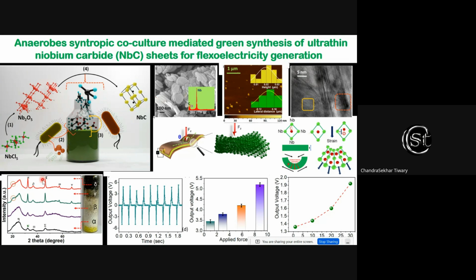Now the X-ray, and this is the reactor, it can clearly show this was the niobium chloride salt which we started with. It converts into oxide, and then slowly, because of the presence of microbes, it starts becoming black color niobium carbide, which can be utilized for energy harvesting, as a coating, and so on. And all of this material, the size, thickness, and dimensions are almost similar to each other. Extending the work, as we can make different kinds of 2D material, we can make a nice suspension of this 2D material, we can produce in large scale, and we can produce in an energy efficient way.